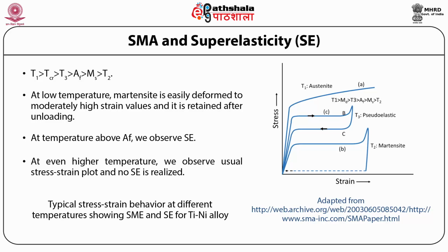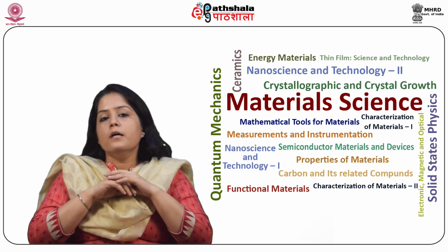This is a critical temperature termed as MD, above which the superelasticity behavior is lost and the material behaves like the usual structural material.